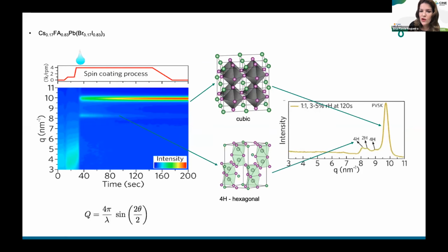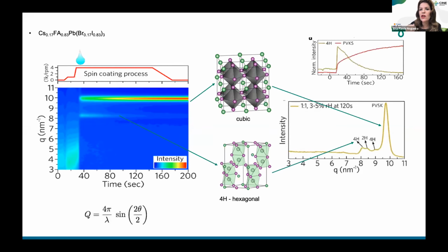What's interesting is that, as we're doing this as a function of time, you can plot the intensity of these peaks with time. And you see clearly that first we are forming these hexagonal phases, and then these hexagonal phases are actually converted to the perovskite.